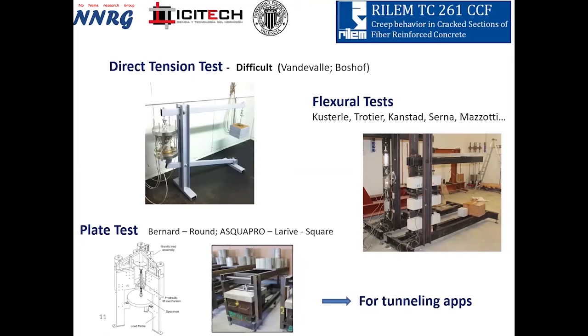And then we have a test thinking on direct tension like this, a specimen where you apply a constant load and you maintain that. Or you make a test with elements working in flexure in 1, 2, 3 different shapes. This is the most frequent in the research market. But when you are working in tunneling, usually people use square panels. Then you make a square panel supported on all the contour and apply a central loading, thinking in the effect of supports on the tunneling concrete.